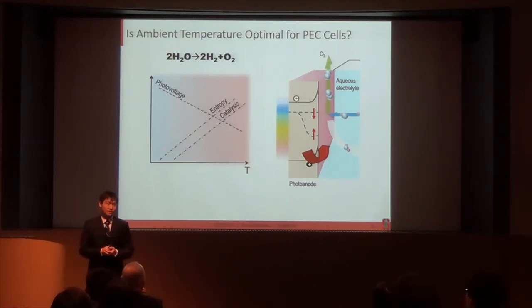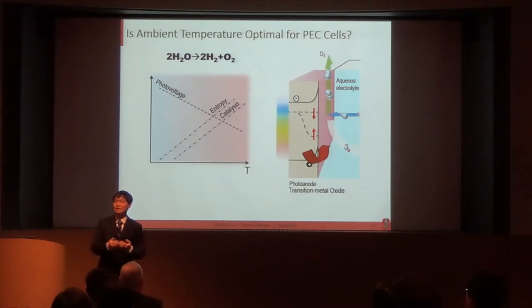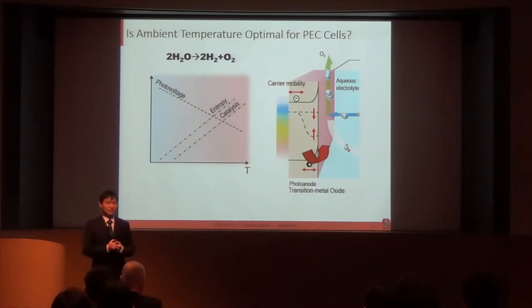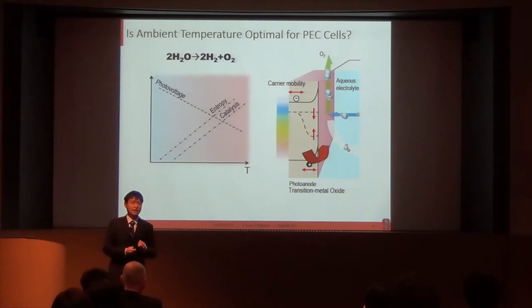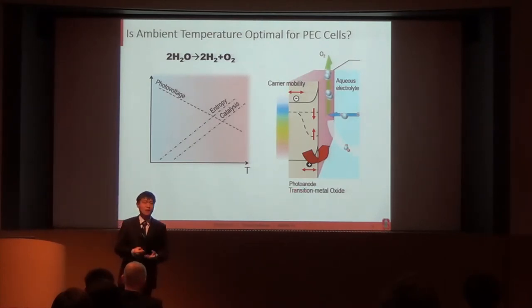So what else? As I read more literature, I realized that the materials that people use in this photoanode are quite different from traditional semiconductors like silicon. These are transition metal oxides. They have very different material properties and very different temperature dependence. One of the biggest differences is the carrier mobility. The carrier mobility describes how fast the electrons and holes can move within the semiconductor. In silicon, for example, these carrier mobilities are already very fast at room temperature. They actually decrease slightly with increasing temperature. However, in these transition metal oxides, the carrier mobility is quite slow at room temperature, but strongly activated by thermal energy.